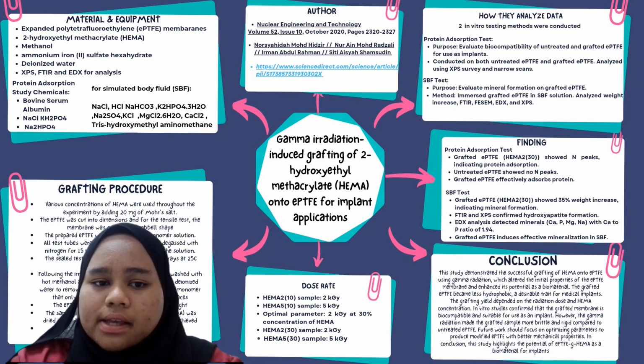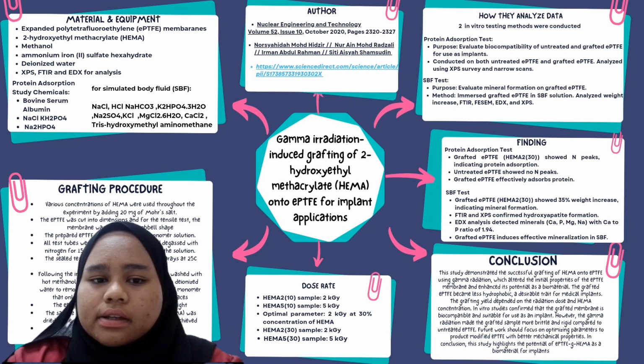FTIR and XPS analyses confirm hydroxyapatite formation, while EDX analysis detects minerals like calcium, phosphorus, magnesium, and sodium, with a calcium to phosphorus ratio of 1.94. So the grafted ePTFE induced effective mineralization in SBF.